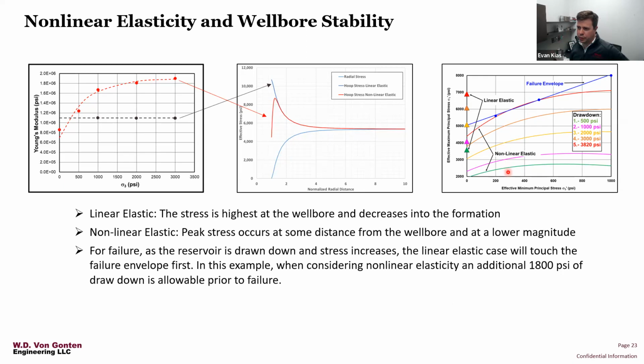drawdown pressure required in order to fail the rock at the wellbore, in the two different cases, we see the improvement. In the case shown with the linear elastic model of the rock, the well is drawn down 2000 psi, and you can see at the wellbore surface the stress state has touched this failure surface. Whereas in the nonlinear case, each one of these lines is showing the drawdown stress, and we can achieve an additional 1800 psi of drawdown before the stress reaches the failure envelope. So a big difference, and by not considering this nonlinear elastic behavior, we're certainly doing a disservice to our understanding of the situation.